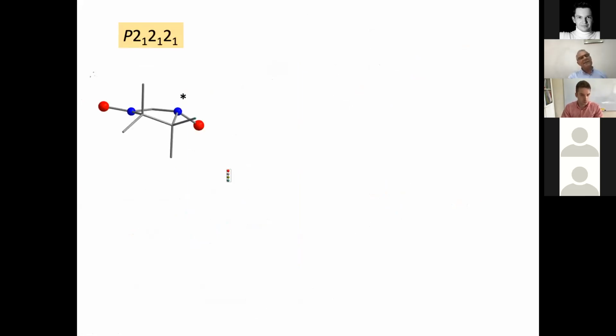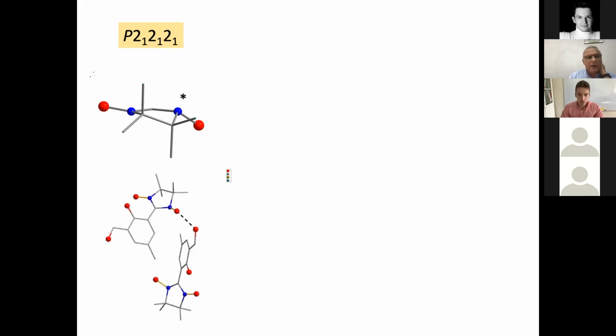This compound crystallizes in a non-centrosymmetric space group, and the explanation is the fact that this nitrogen atom is chiral and this oxygen atom is involved in a quite strong hydrogen bond interaction, but I'm not sure that this is the origin of this strange geometry, because we have other hydrogen bonds involved in this NO group. It's true, a bit longer, and the fact that the molecule crystallizes in a non-centrosymmetric group means that we have to analyze carefully what happens in the crystal.